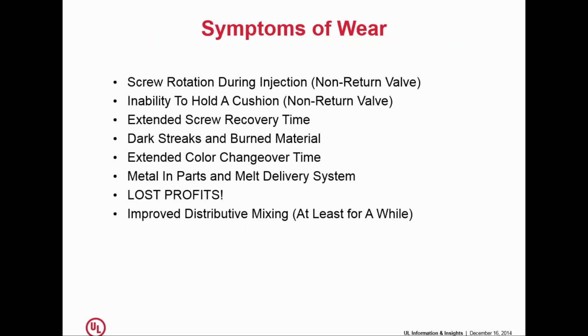Now, symptoms of wear. You may see screw rotation during injection. This is probably the check ring, the so-called non-return valve, which we'll talk about in a minute. The inability to hold a cushion, also usually the problem of the non-return valve. You may see extended screw recovery times. You may see dark streaks and burned material. You may see extended color changeover times, even if you're using a good purging compound. You may start to notice tramp metal in your parts or in your melt delivery system. These are all signs that things are starting to wear out.